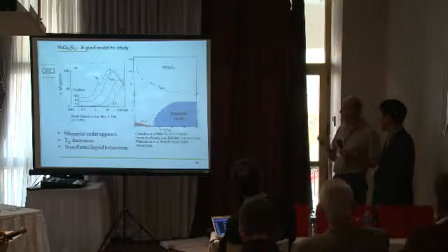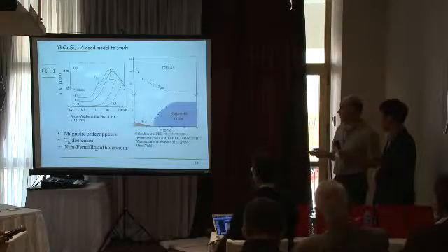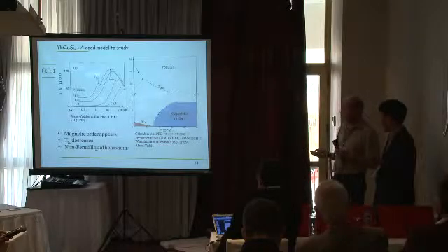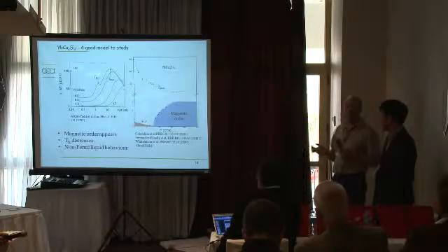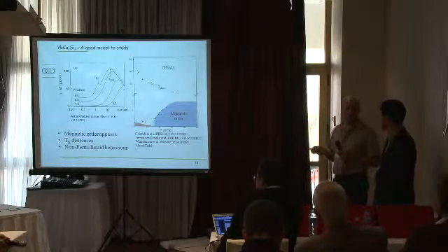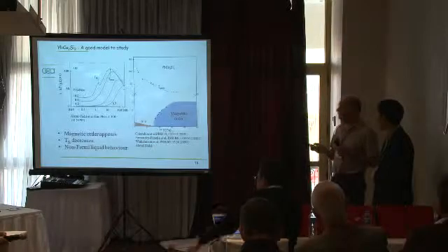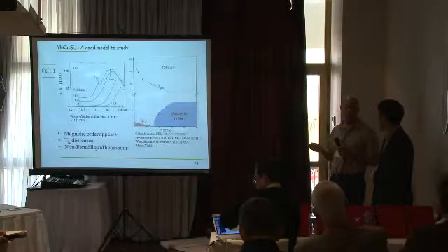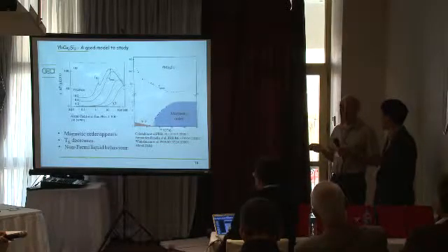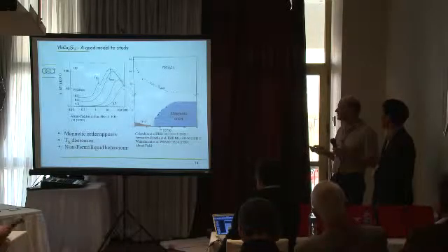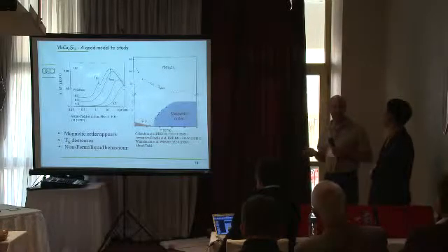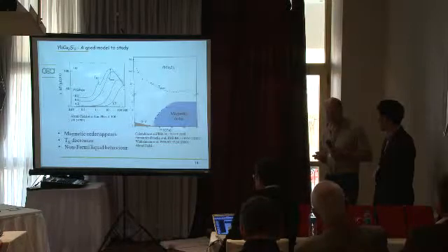Yes, if we look, for example, at resistivity, in this region we have a Fermi liquid behavior. If you follow the T-square coefficient, this is increasing very strongly, about two orders of magnitude between zero pressure and critical pressure. Then, what you would expect normally in a magnetic state is a decrease again. This it doesn't do. It continues to increase slowly. This is a strange behavior.